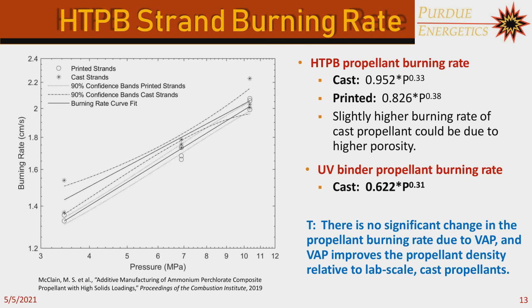Slide 13. So the next thing that we did was some high pressure experiments where we compared the burning rates of cast HTPB propellants and printed propellants. And essentially what we saw is that there's quite a lot of overlap in the points, so there really is no significant difference in the burning rate. The cast propellant might be slightly higher in burning rate, but that is only because it is slightly more porous based on the density.